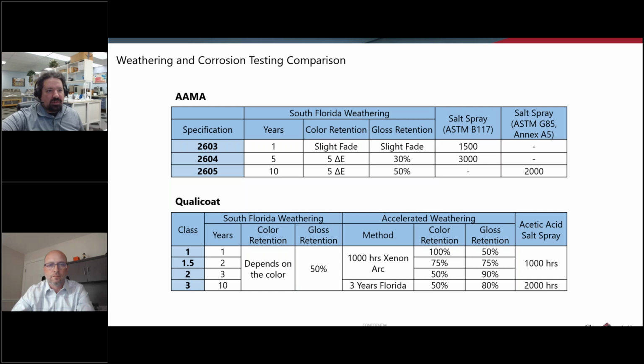The difference with 2605 is that it's called ASTM G85 Annex 5 or Prohesion. It's a more dilute solution, but it's also acidic, and instead of constantly running the fog, there's an hour of fog and then an hour dry off period at an increased temperature. And so it's really aggressive. You'd think that just spraying salt on things 24 hours a day would be pretty aggressive, but actually going through the process of fog and then drying, fog and drying for 2,000 hours is a pretty aggressive test. And so that's what they expect for the highest level of protection.